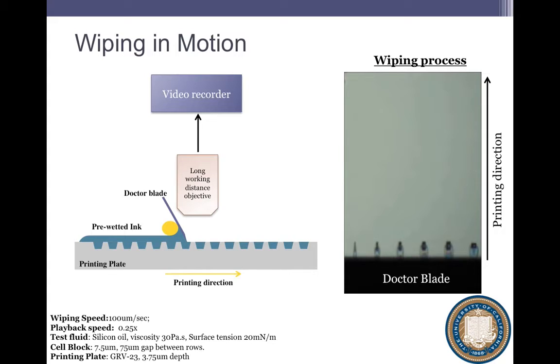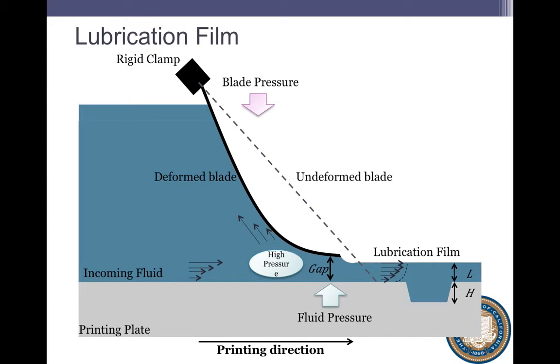So I now get to give you my second process rule. My second process rule, because it is a wetting-based process, in one of those weird things that happens in the world very rarely, is that wiping actually works better when you go fast, because it doesn't wet as much. Unfortunately, life is a little more complicated than that. If you go too fast, there's so much pressure that builds up in the fluid that it'll actually deflect the doctor blade up. There's huge amounts of pressure. Our blades are made of stainless steel, and they still get deflected up, and then you deposit this sort of uniform lubrication film. It turns out it models really well by lubrication theory. A lubrication film gets deposited behind it. So I'm going to modify my second process rule. My second process rule is wiping works better when you go fast, but not too fast.